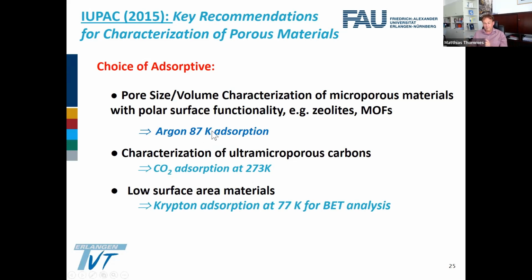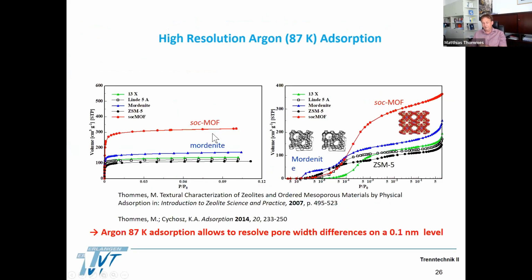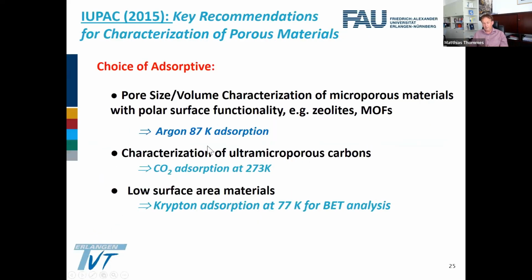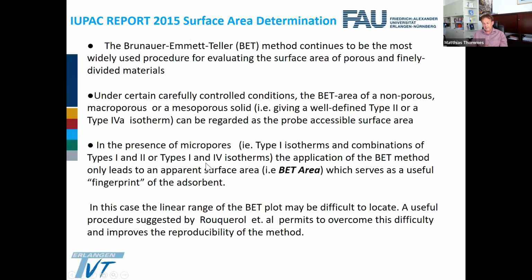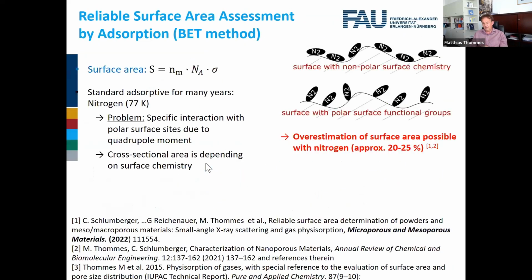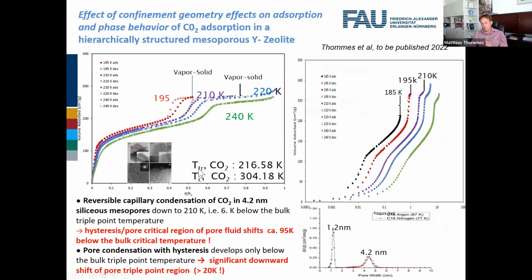So let's stay with this very quickly, just so people who have not seen this. Here comes another very important point which I want to make. And I had a slide before which essentially demonstrated this, the importance of looking at your data. This is for the experimentalists: particularly when you look at data which have micro and mesopores in the system, particularly with micropores, it's extremely interesting to plot these data in a semi-log plot. This allows you to see the quality of your data, but particularly the structure of your porous system.